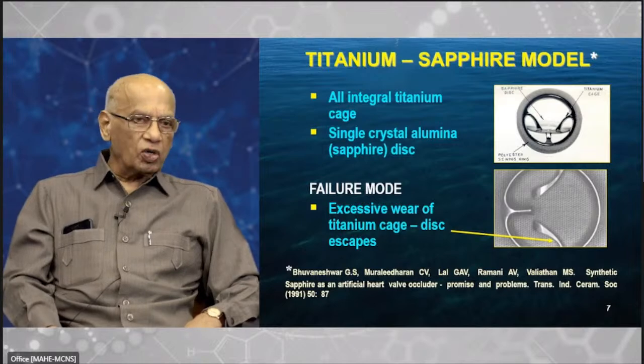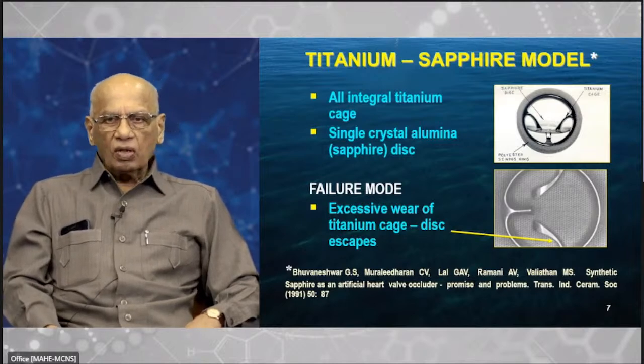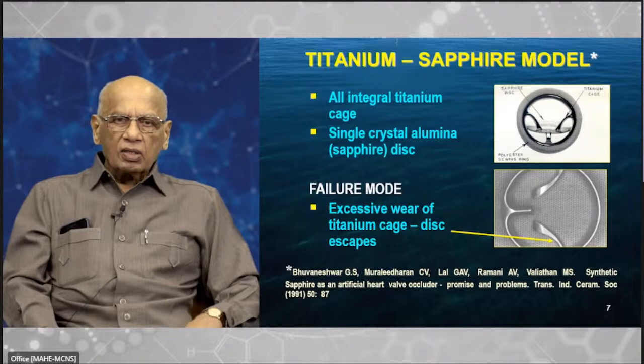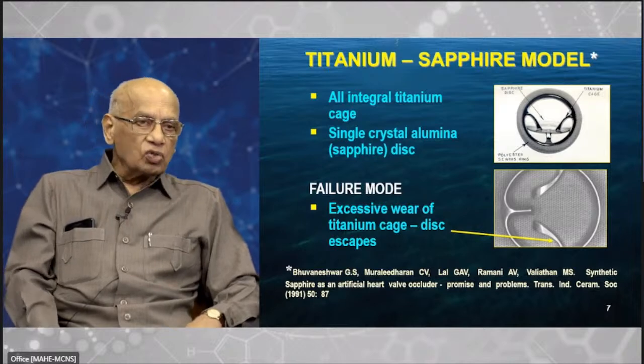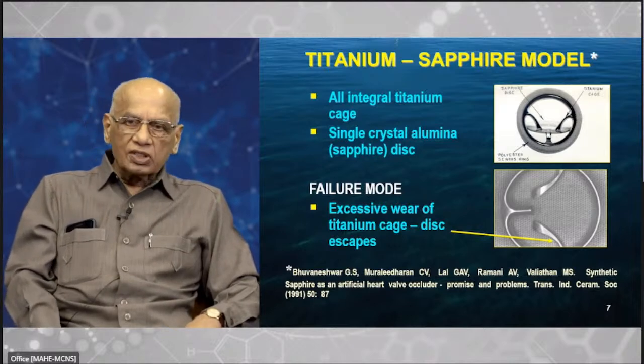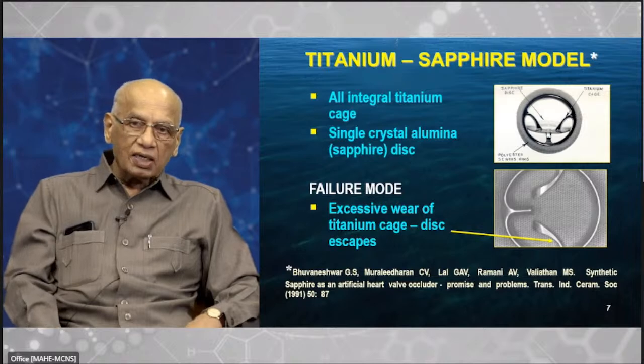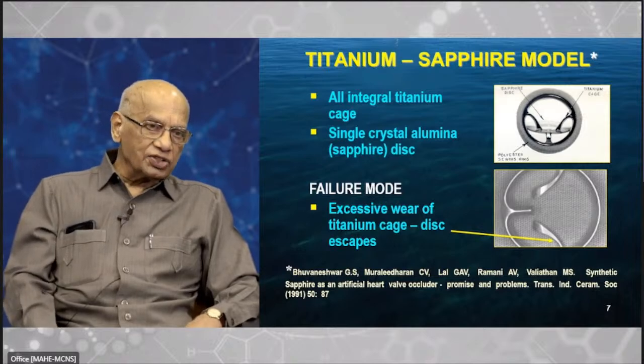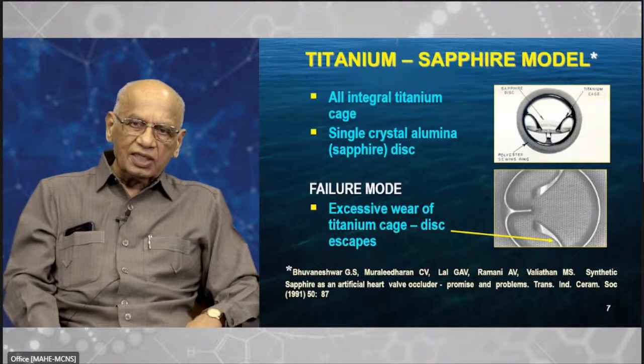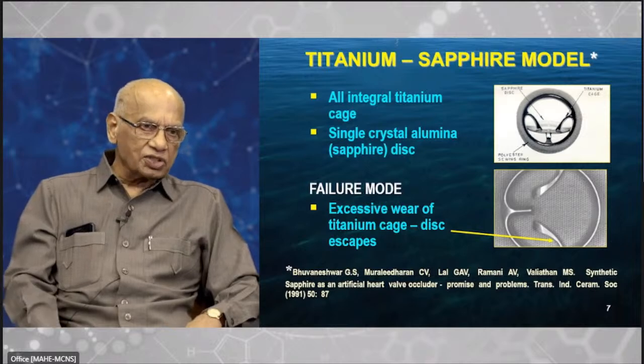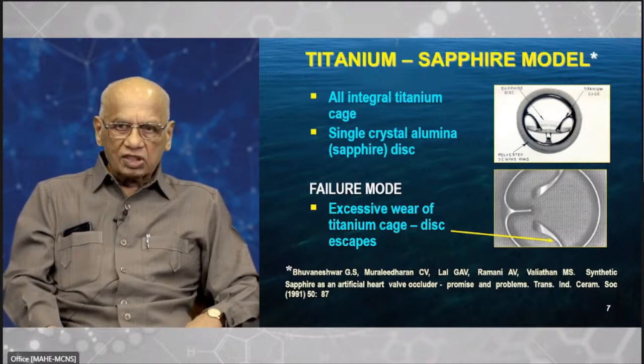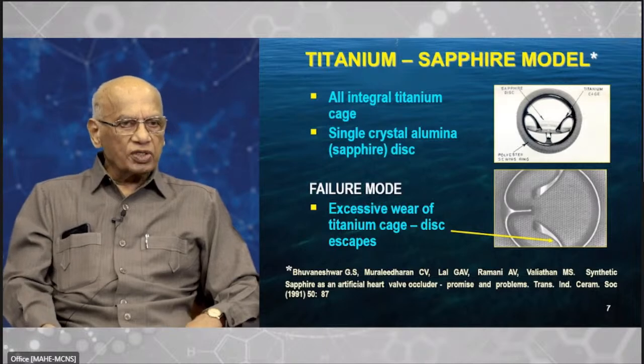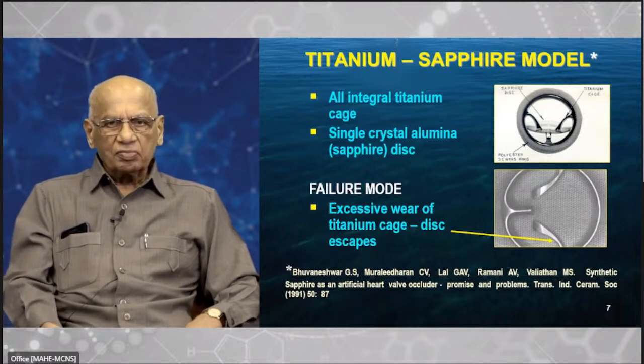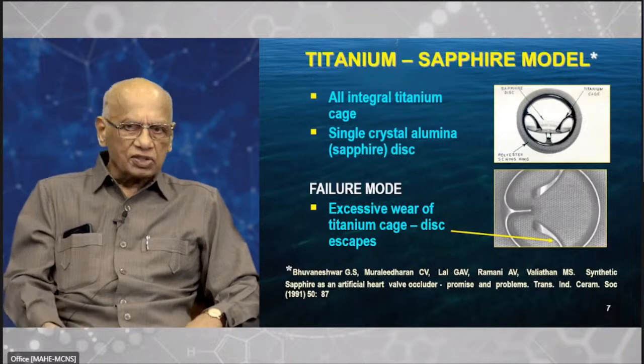Now, this is the next model, model 2. Here, the all-integral cage, there is no welding anymore. The struts are integral to the cage. There are 3 independent struts, not bridged struts. And the disc is suspended in between the struts, opening and closing. That is one very big change. Otherwise, the sewing ring remains the same.